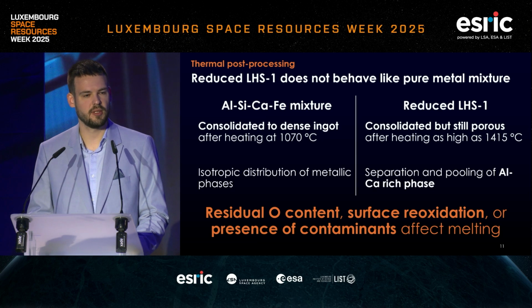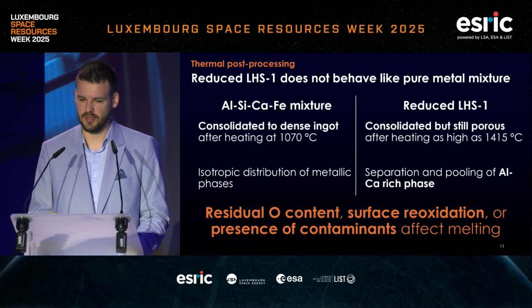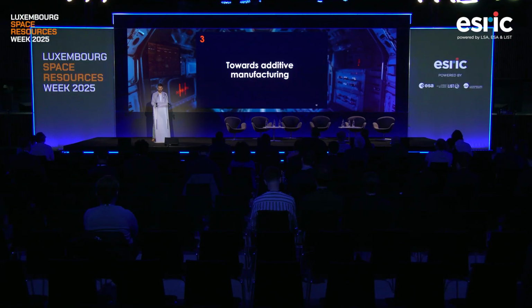So to conclude on that part of the talk, we expect that we have some elements in the reduced regolith that prevent the melting. Our main suspects, let's say, are the residual oxygen content. We still have over 1% oxygen in there, so 1 to 4 weight %. It could also be surface reoxidation during the post-processing, as well as the presence of different contaminants. I'm thinking stainless steel components from the reactor. So still some investigation to do there, but we still continued pushing forward in parallel, and we started looking at the end application, the additive manufacturing.